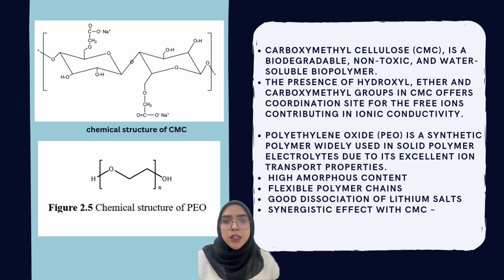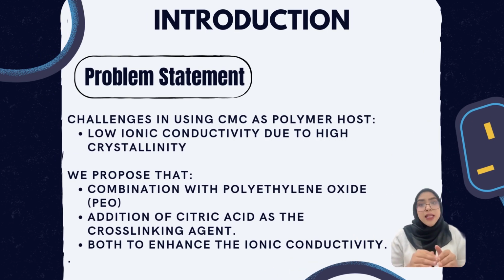to its excellent ion transport, because it has a high amorphous content, flexible polymer chains, good dissociation of lithium salts, and a synergistic effect with CMC, since CMC has a highly crystalline structure and PEO has a more amorphous content than CMC. Okay, the problem statement for this experiment: even though CMC has a lot of benefits, it also comes with challenges, which is that it has low ionic conductivity due to high crystallinity.